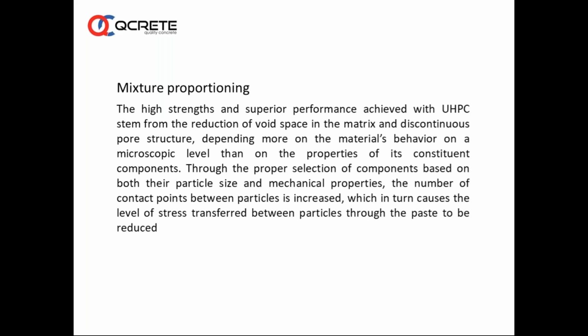The high strength and superior performance achieved with UHPC stem from reduction of void space in the matrix and a discontinuous pore structure, depending more on the material's behavior on a microscopic level than on the properties of its constituent components. Through the proper selection of components based on both their particle size and mechanical properties, the number of contact points between particles is increased, which in turn causes the level of stress transferred between particles through the paste to be reduced. So mixture proportioning of UHPC is not like conventional mix design or mix proportioning.